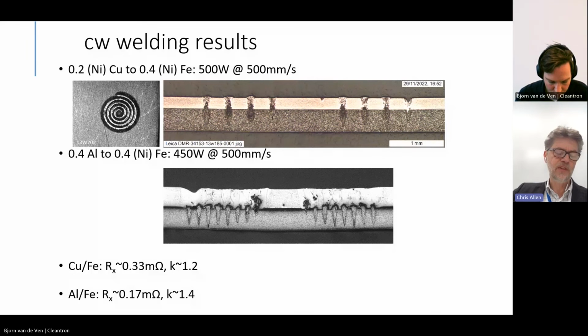So you can see there, for example, that the aluminium to steel joints are that little bit more relatively resistant than the copper to steel joints. And some of that is to do with the materials that are being used, but some of that is also to do with aluminium iron intermetallics, which form in that particular combination of materials, and that we don't get in the copper to steel joints. Next slide, please.